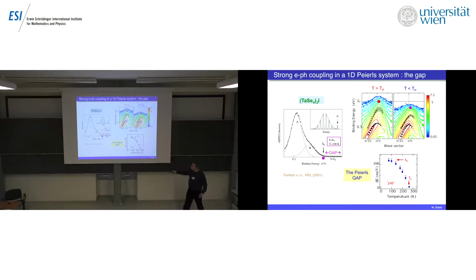And in fact, this is quite consistent with the fact that as a function of temperature, as one reduces the temperature through the Peierls transition, there is a gap opening, and if we track the leading edge of the spectrum, which doesn't have any peak, well, the leading edge reproduces nicely the Peierls gap. So indeed, these are examples of very strongly interacting electrons with the phonons.